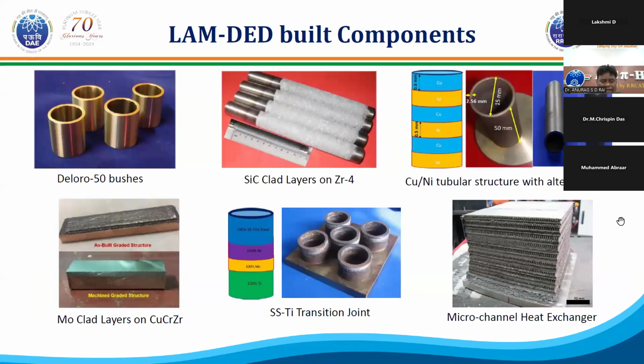If we talk of the DED components, we have built many components. You see the pictures I'm showing you: Deloro 50, silicon carbide clad layers, copper nickel alternate layers. This is a beauty. You can have 50 alternate layers of copper and nickel, and each layer is of 500 microns, and these things can be used for thermoelectric generator TEG applications, which is not possible otherwise. You can't have all these things built together otherwise. Similarly, moly clad layers on copper chromium zirconium is done.